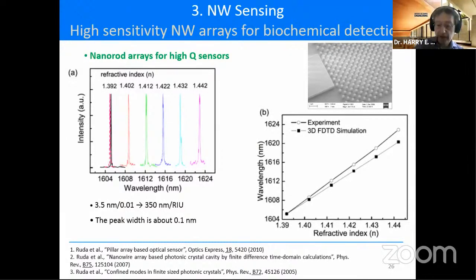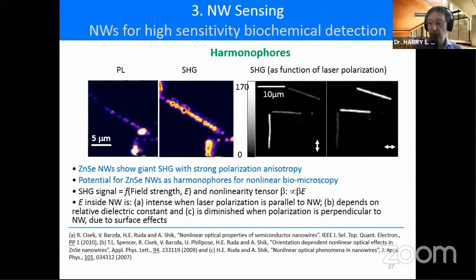All right, so the next thing in the optical domain I wanted to talk about is it doesn't have to be a linear response. Non-linear effects are also very strong in these kind of nanowire structures, and part of that is the polarization anisotropy due to the way refractive index is set up in these structures, and also part is due to the way charge is distributed. And we go back to the screening and surface state occupation here, which means that one has, in this case, very strong nonlinear response.